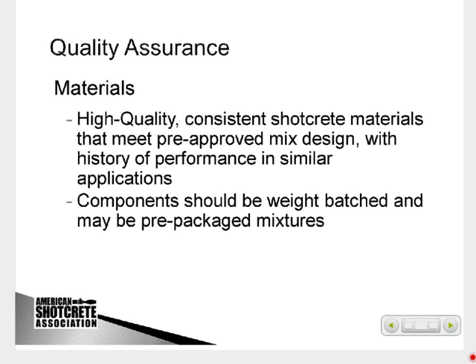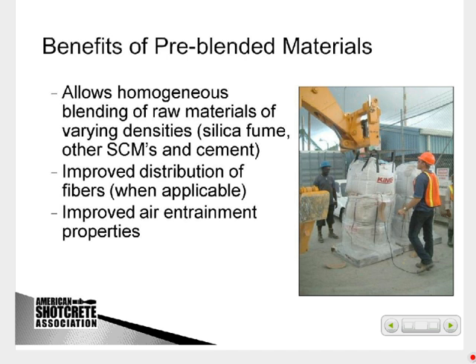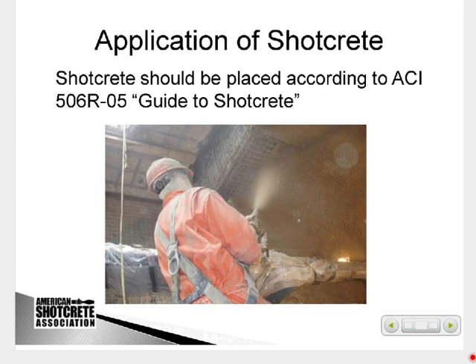Quality assurance, you need to be sure that if it is site batch that you get your weights. There are volumetric mixers, but they need to be calibrated so you get the correct weights. But in shotcrete, we have seen a move towards a lot of pre-bag mixes. Even some small wet mix applications, they'll get those big super sacks, mix it on site, so just adding water at the site and then pumping it with a concrete pump to make wet mix process. That has the advantage of basically control. You're not at the mercy of a concrete supplier in terms of their truck getting batched and then getting to your site.